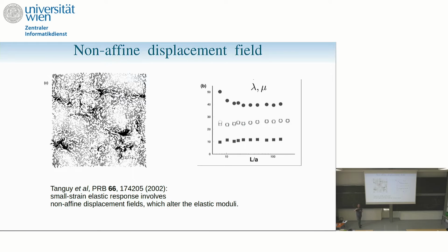We could imagine that if we shear a system, we know the potential of interaction between atoms. So we want to calculate the elastic response. A way to do this is to assume that all the pairs of particles are changed according to the macroscopic strain, and calculate the resulting elasticity. What happens is that if you do this, you find Lamé constants that are equal, in 2D, and it's the same in 3D. That's a problem, because you cannot have a big variety of Poisson ratios.